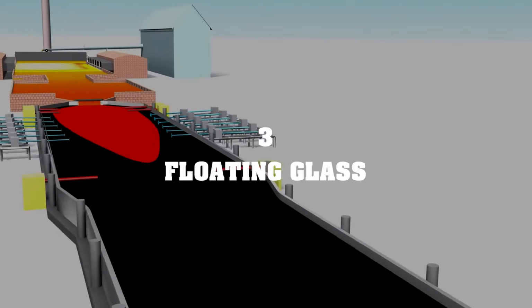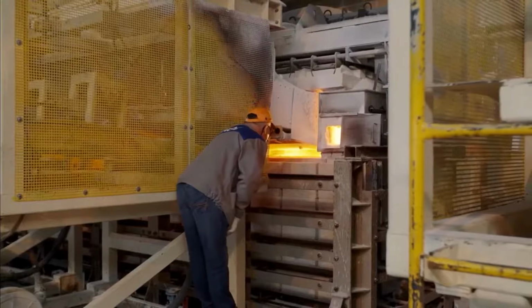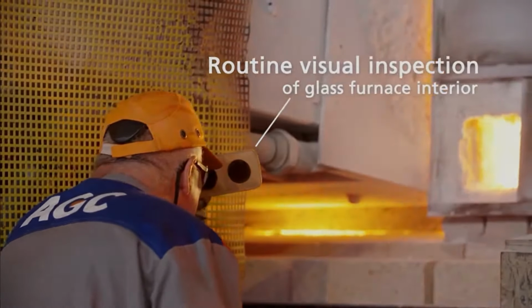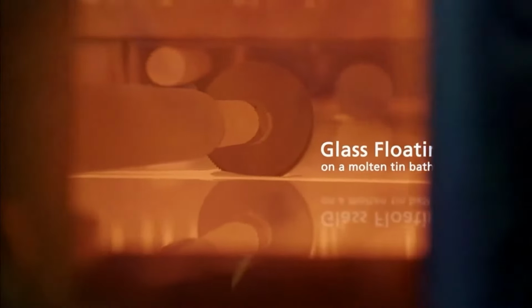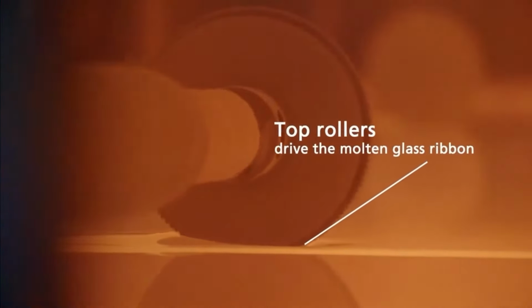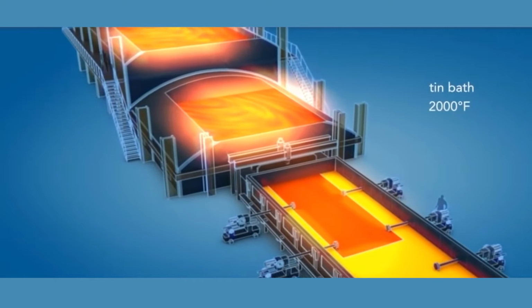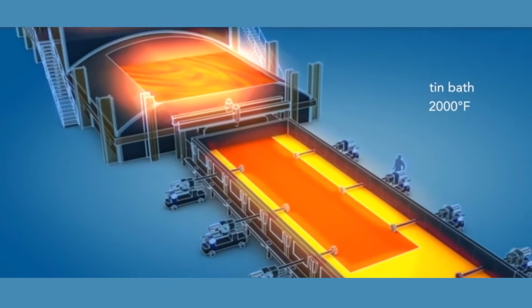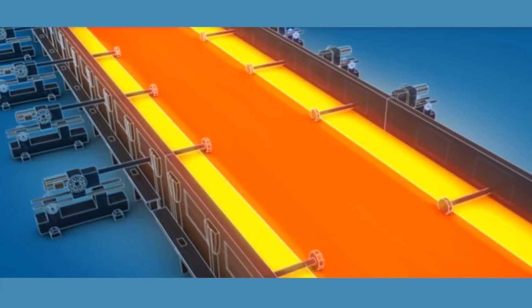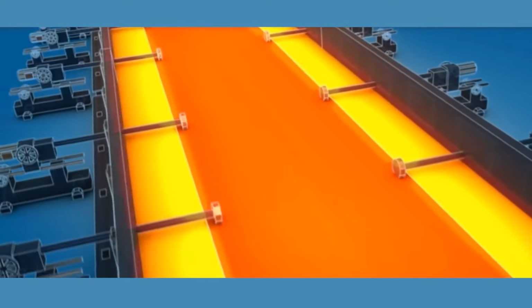3. Floating glass. Drawing on tin bath. The molten glass is then floated onto the molten tin bath at around 1000 degrees C. The glass flows on the surface of the molten tin to form a long, smooth glass ribbon on both sides. It forms a ribbon, typically sized from 5 to 6 mm. By pulling the glass appropriately through a complex process involving the rolling machine on top, ribbon thickness can be achieved from 1.9 mm to 19 mm.